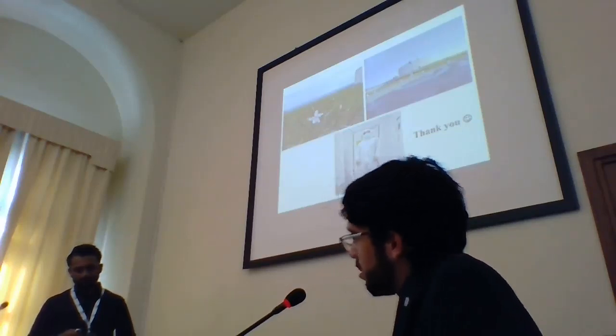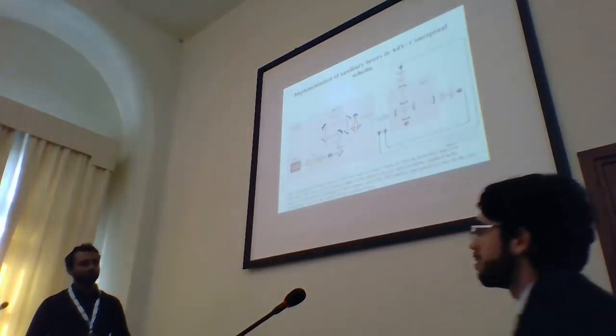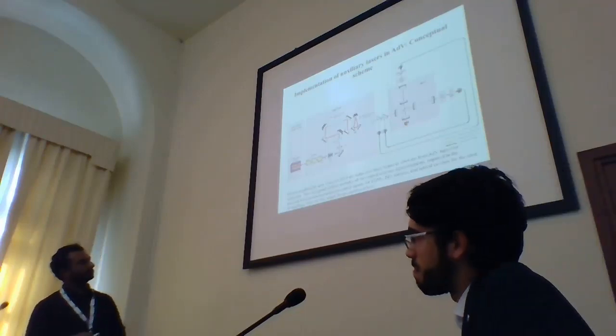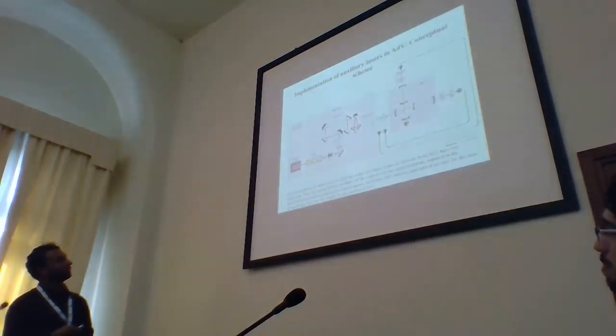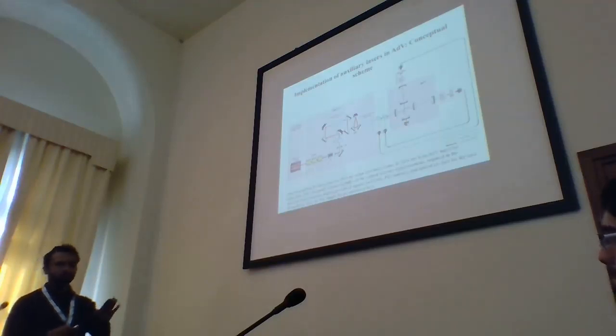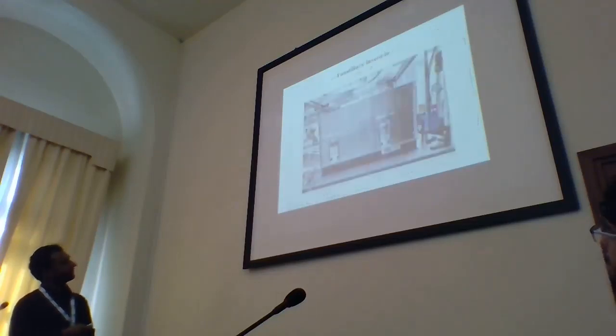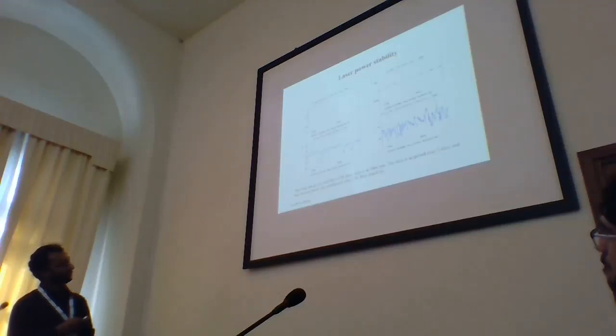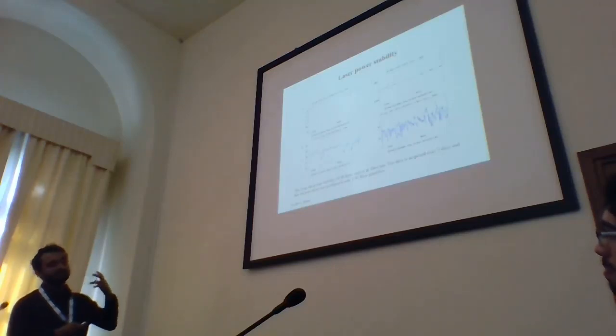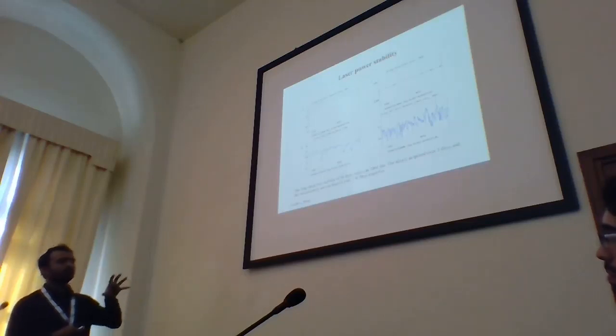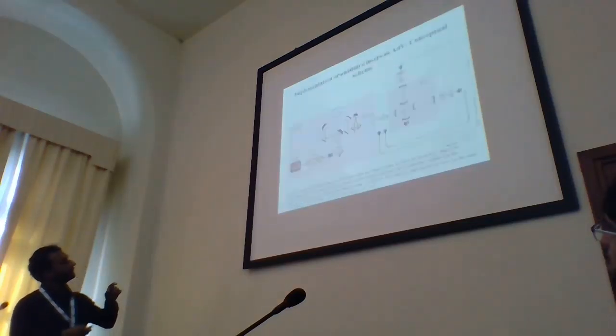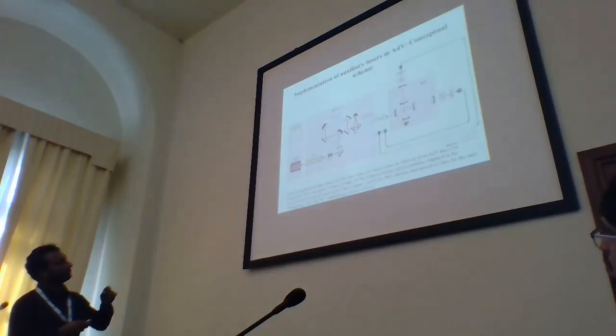Okay, sure. First of all, the Virgo environment is almost homogeneous all across its premises, if I have to talk about the entire detector. So eventually your environment is going to be almost the same on the 2 arms, the 2 end test masses. Now this power stabilization loop, which allowed us to take data over 5 days of measurement, was giving us this very stable intensity stabilization. So what we are looking after is the intensity stabilization, so we can easily rely on this. This is a kind of local power stabilization loop which you have to implement just on part of the bench, which will be implemented here. So it has nothing to do with the rest of your interferometer.